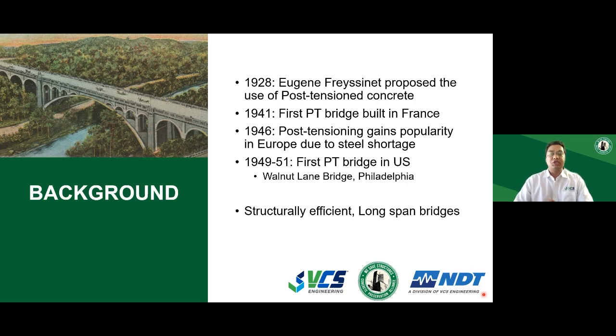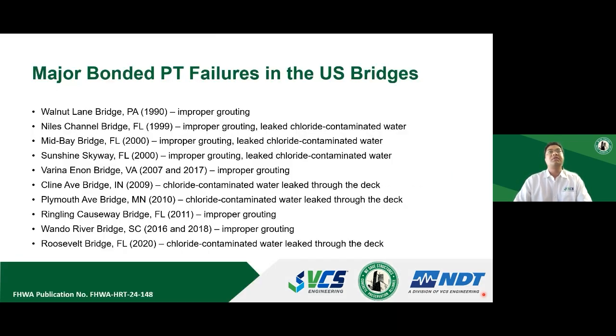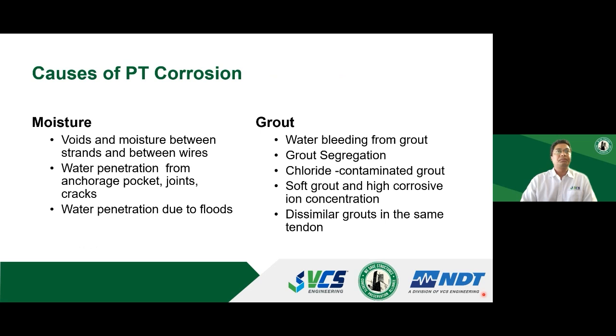In terms of history, I'd just like to briefly go over the major failures that have happened in the history of US bridges. And if you note all of these failures, most of them or almost all of them can be attributed to either improper grouting or ingress of chloride contaminated deck runoffs. So essentially, when it comes to durability of post-tensioning structures, what matters is the homogeneity of the grout in the vicinity of the tendons and the voids, or how well they were poured in.